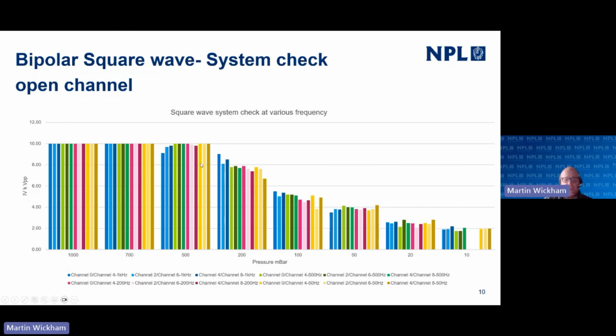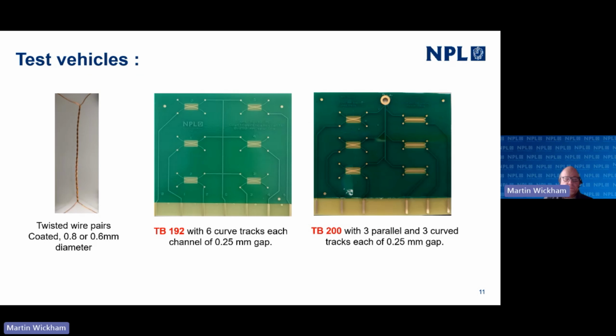You can see here that the PD on the system at 200 millibar is above 7 kV and it's above 5 kV at 100 millibar. These are the sorts of test samples we're working on. These are just effectively single-sided PCBs with tracks in. We connect to the ground level, ground here and here, and then we apply our bipolar square waveform across these connectors here, and so across these curved tracks.